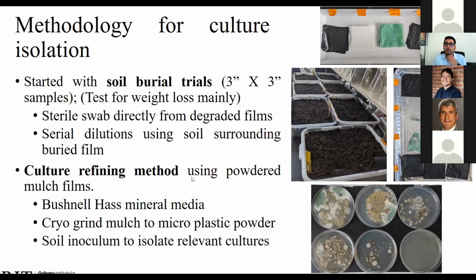Here we used a powder of the plastic instead of the whole plastics. And the method has 3 main components: using a mineral media, which is nothing but a salt media. It does not have any carbon source. The mineral media we chose is the Bushnell-Haas mineral media. It was originally used for studying biodegradation of hydrocarbons, and we thought that might be a perfect media to test our films. And again, we cryo-grinded the mulch films into microplastic powder, thus increasing the surface area and reducing the size massively. And finally, we use the soil, which I talked about, as an inoculum to isolate the microbes which we wanted.